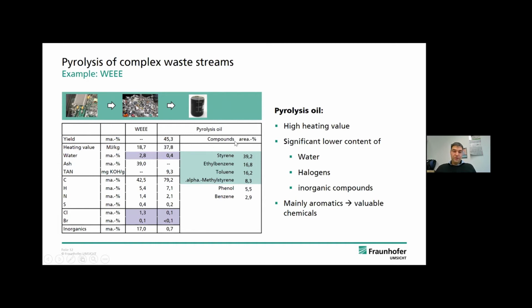However, if we have a look at the composition of the oil, we do see a very high amount of aromatic compounds. So we have up to 40% of styrene. We have quite a lot of ethyl benzene, toluene, phenol, and benzene. And in our eyes, these compounds are too valuable to use them for energy recovery. So we think these chemicals should be first isolated, and the rest could go, for example, into steam crackers, but should not be used as a fuel or for energy recovery.